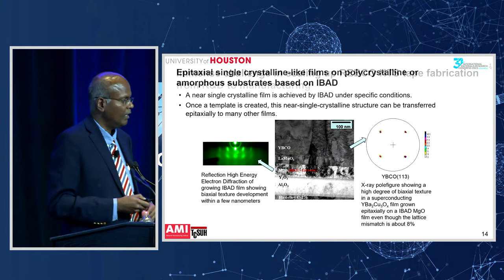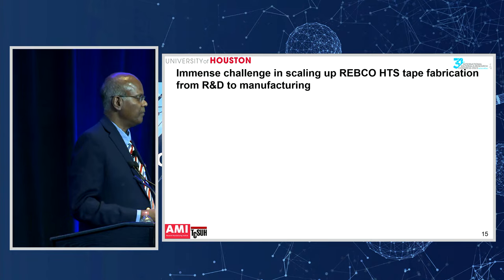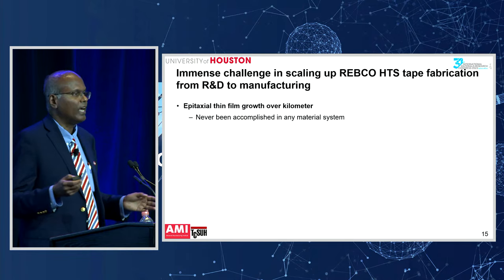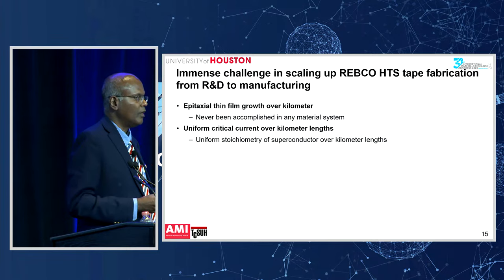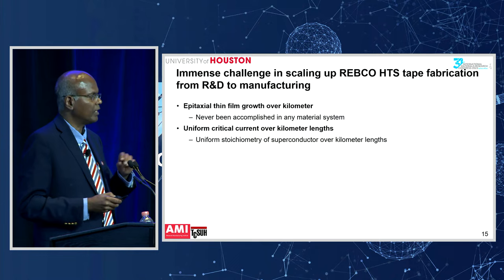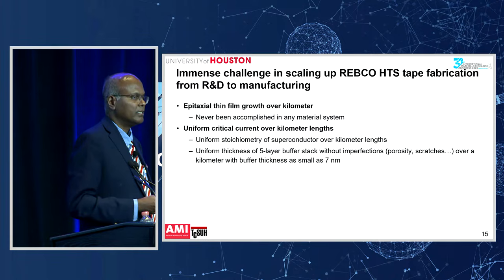However, that is the technology development. But then how do you scale up to manufacturing? There are many, many challenges in scaling up to manufacturing. You have to grow this epitaxial film over a kilometer. It's never been done in any system, to my knowledge. And then you have to achieve uniform current over long lengths, which means you need to control the stoichiometry and composition of the film over kilometer lengths. You need to maintain the thickness of all the different buffer layers, which is typically nanometers thickness, over kilometers.